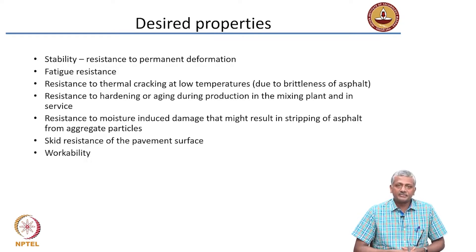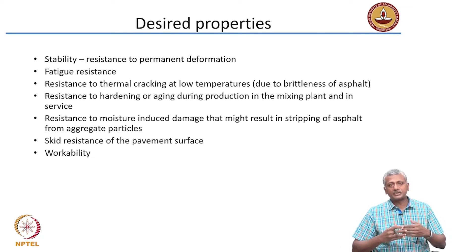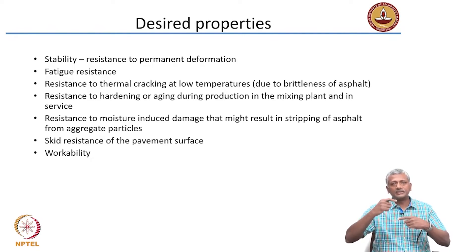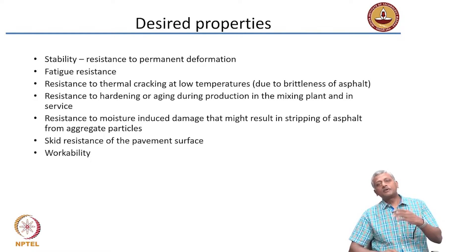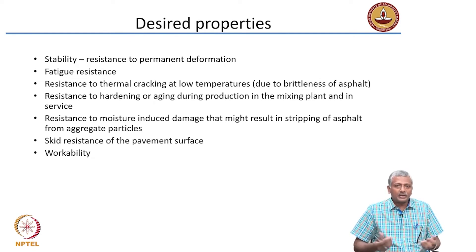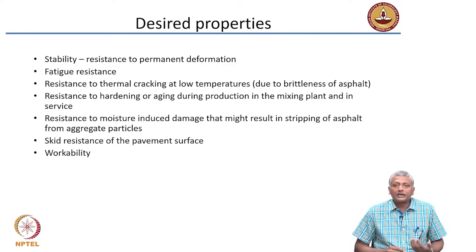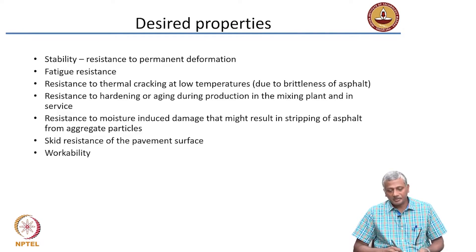Fatigue resistance is important because highways experience continuously moving loads — not one static load, but continuously dynamic, replenishing loads. You need to understand the number of cycles the pavement material can undertake without collapsing. At low temperatures, the polymer becomes brittle and starts cracking, so low-temperature thermal cracking resistance is very important.